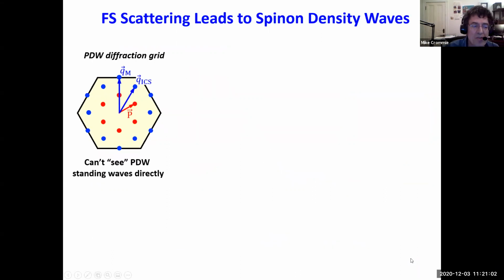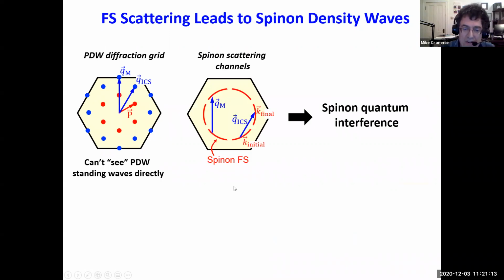The problem is that we don't actually see the pair density wave, because when we tunnel electrons in, we're only creating a single spinon, not 2 spinons. But you have to remember that there's still some ungapped spinon Fermi surface left, and these spinons are going to scatter off of the pair density wave density because of the gauge interaction, and so they're going to reflect the wave vector of the pair density wave because of quantum interference.